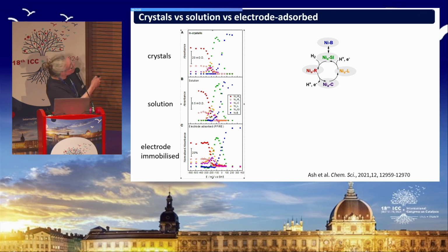And what really struck me was that this top one is in crystals, the middle one is with the enzyme in solution, and this bottom one is with the enzyme adsorbed on an electrode surface. And the speciation curves look almost identical between all of those. And that shows us that we can really think about this crystal environment as being very relevant to the behavior of the enzyme in solution, or indeed on an electrode surface, if you like. But it shows us that we're really getting dynamic behavior of the protein in the crystal, which allows us to navigate between all of these states that we observe in solution and that are relevant to catalysis.